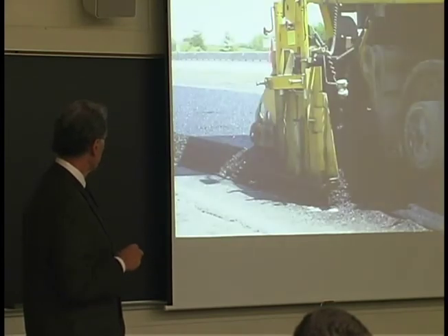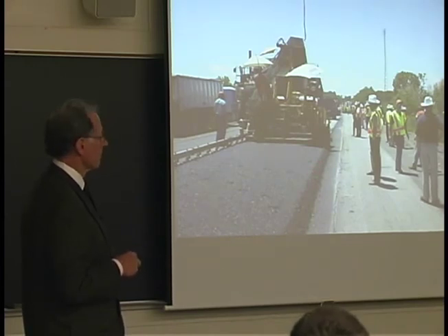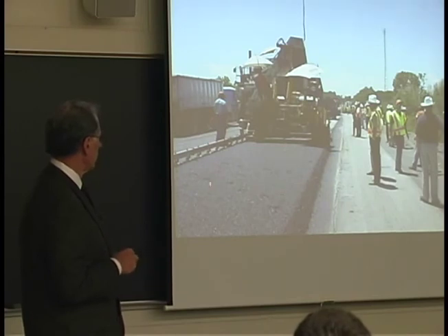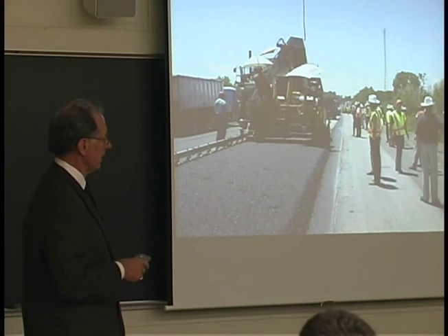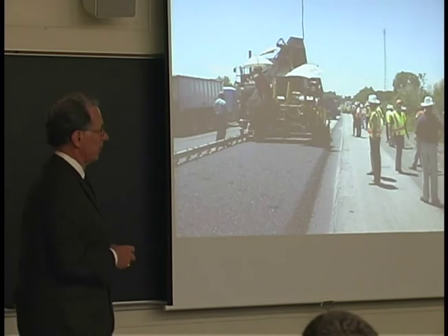This again was when we were laying the 6-inch lift of asphalt. And here again, you can see how thick that lift of asphalt was. The next layer would blend to this after it hardens? Yes, absolutely. It will normally adhere to it very, very well. Down here on Interstate 70, because of the traffic volume, we did spray prime, and that's a prime truck right there. We sprayed prime on every single lift to give it more of an adhesive. On a normal roadway, you may or may not do that depending on what the state specs are.